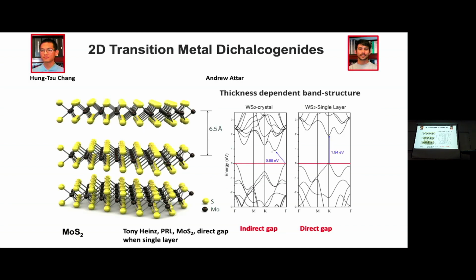So now let's think about 2D metal dichalcogenides. And 2D metal dichalcogenides could be like molybdenum sulfide, and you would put it in your lock as a good lubricant, right? For years and years, it's black, you think it's worthless. But Tony Heinz showed if you peel off one layer of this material, it becomes a direct gap semiconductor, which is rather special. So it goes from an indirect gap to a direct gap.